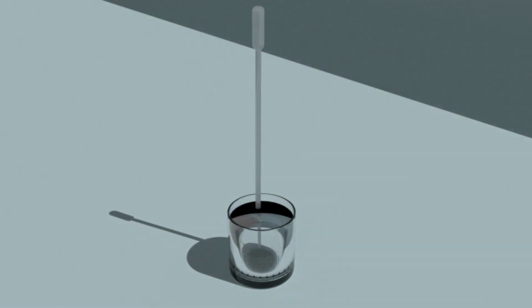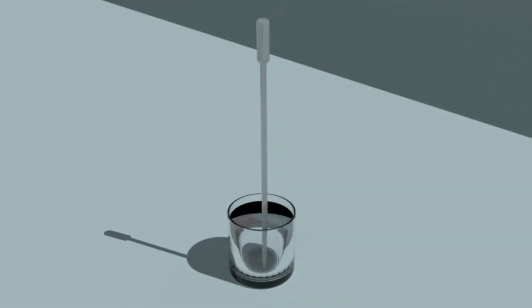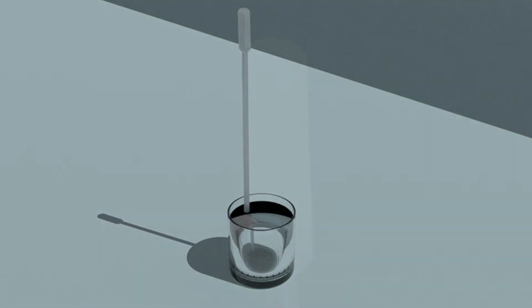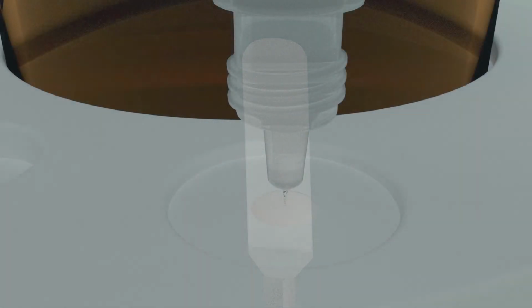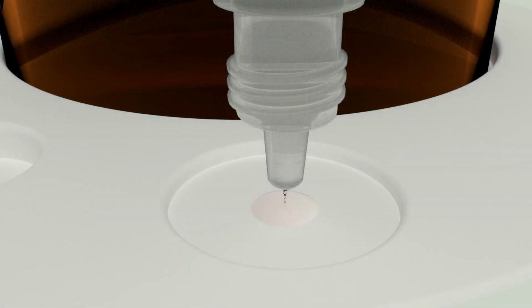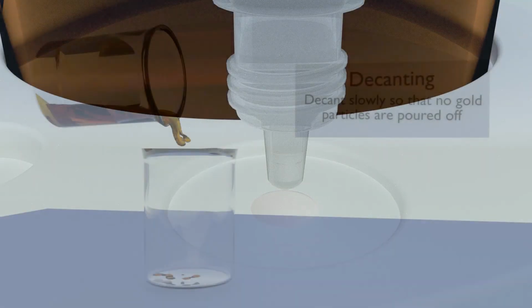Between each test, clean your pipette with water. The inside of the pipette can be cleaned by squeezing and releasing the bulb a few times, while the tip is immersed in water. When your test causes no change in color, that means that no gold remains dissolved in solution, and it is time to recover the precipitated gold.